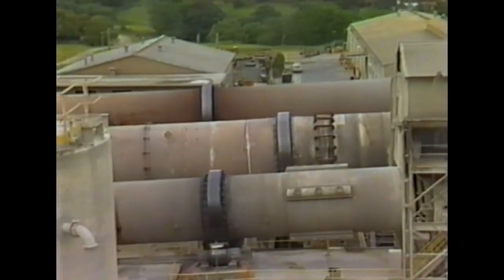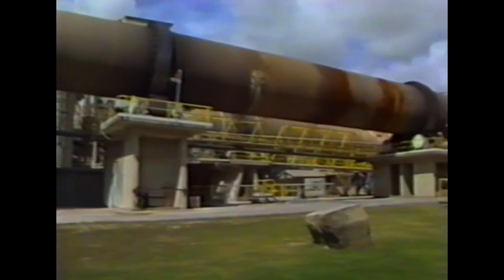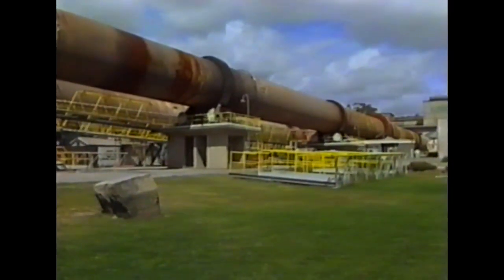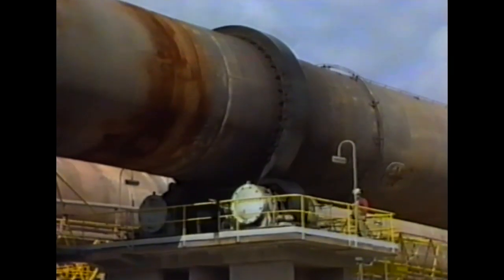The ovens, they're called kilns, are massive, up to 170 metres long and nearly 1,000 tonnes in weight. Tilted at a 2-degree angle, they rotate once per minute. The slurry dries and heats as it progresses down the kiln towards the flame, swirling into the lower end. About halfway down the kiln, at a temperature of about 900 degrees Celsius, limestone calcium carbonate decomposes, losing its carbon dioxide content. As the mix gets towards the end of its journey through the kiln at 1,450 degrees Celsius, the oxides of calcium, silicon, iron and aluminium combine to form clinker.